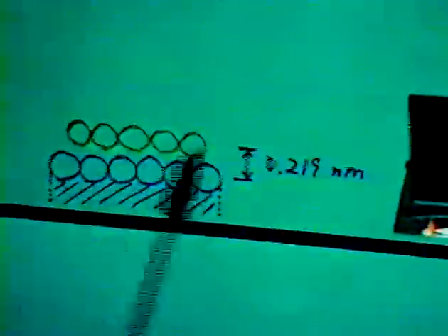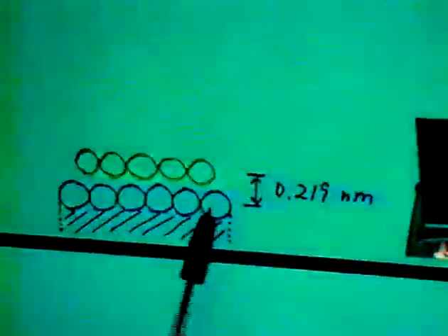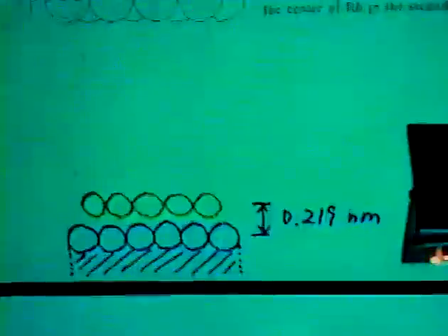The complete refit was performed, showing a very low reliability factor, showing the different bonding for metal-metal bonds. The first peak is 0.268 nanometer with coordination number about 6, and 0.284 nanometer with coordination number of about 3.